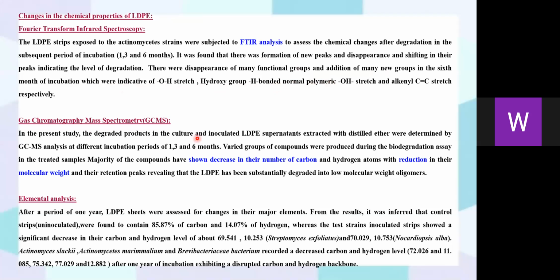GCMS analysis of the degraded products in the culture-inoculated LDPE supernatant was done after 1, 3, and 6 months. A varied group of compounds are produced during the biodegradation assay. The majority of compounds have shown a decrease in the number of carbon and hydrogen atoms with reduction in their molecular weight and their retention peak, revealing that LDPE has been substantially degraded into low molecular weight oligomers.